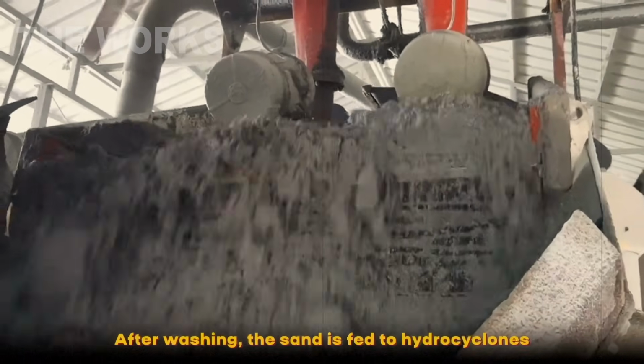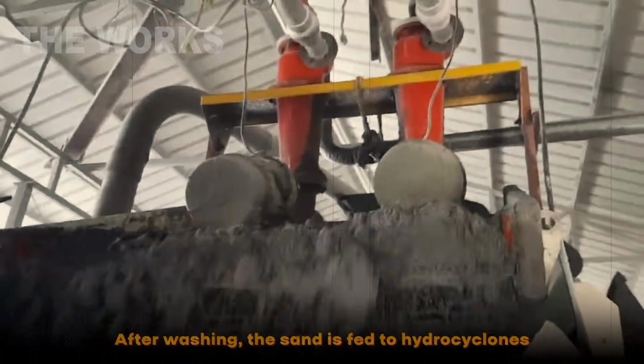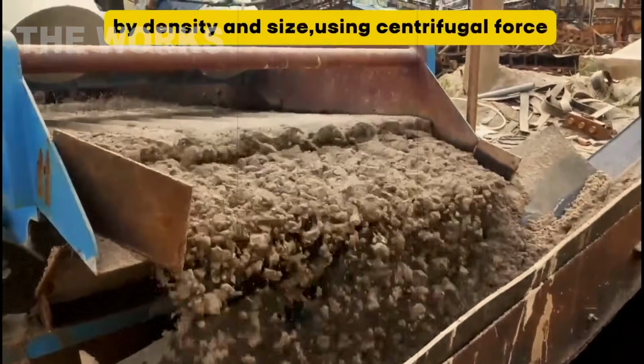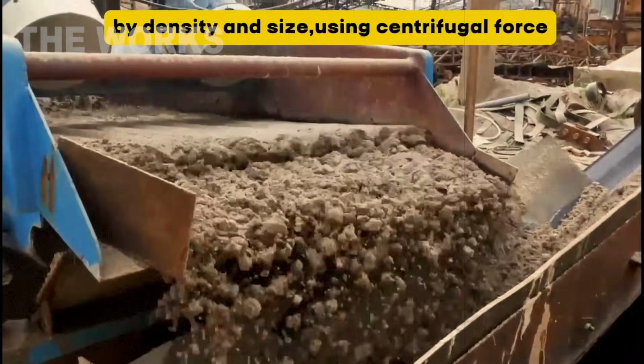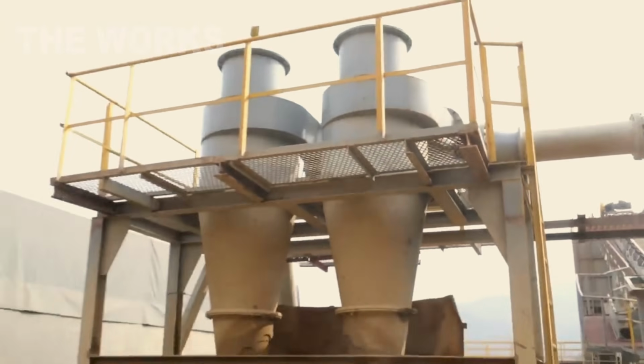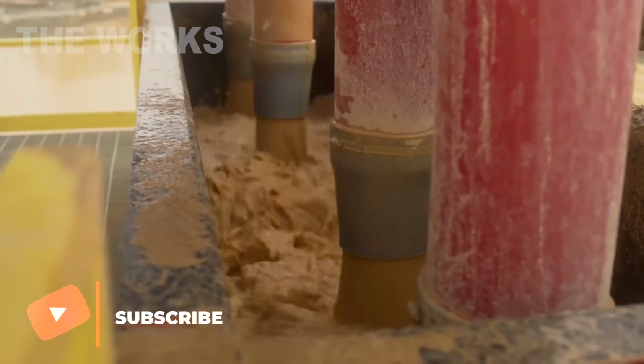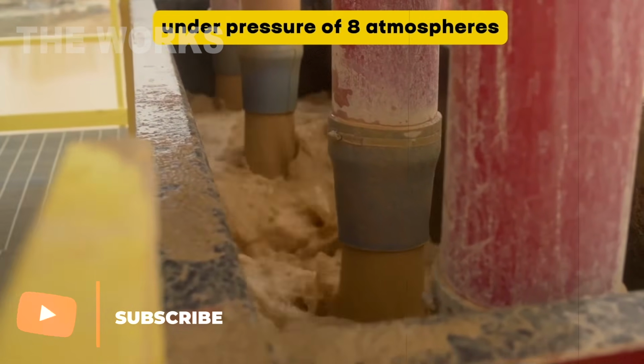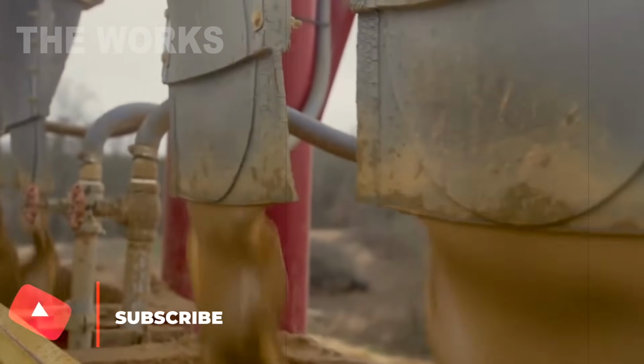After washing, the sand moves to hydrocyclones, devices that separate material by density and size using centrifugal force. Picture giant metal cones 20 feet tall. The slurry gets pumped in at a pressure of 8 atmospheres. Inside the cone, it starts spinning at 300 revolutions per minute.